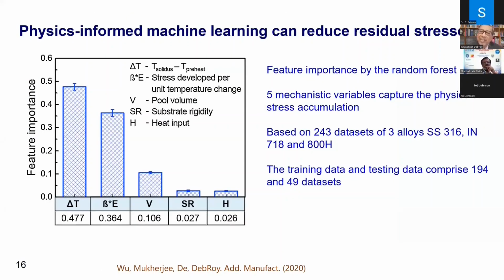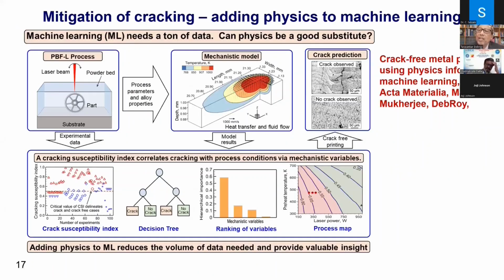One of the benefits that we can get in terms of residual stress and distortion of using those types of routines: we used what is called a random forest model to get the hierarchy of important variables. Here we are showing the temperature difference between solidus and preheat. So preheat temperature has a great deal of influence over residual stress and distortion, more influence than other variables that are listed here. I'm going to explain to you what we mean by machine learning that is augmented with physics. So we are adding physics in order to reduce the volume of data, and that way we can prevent cracking using physics-informed machine learning.